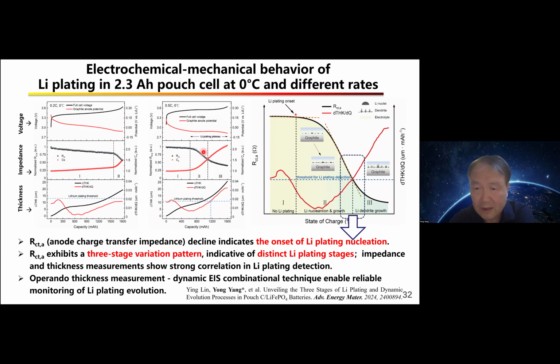We can divide lithium plating on graphite into three stages. One is without any lithium plating, starting at some stage depending on temperature and charging rate. Then there's a stage that correlates quite well with the change in EIS, changing linearly with charge transfer resistance. But at some stage, the thickness measurement can follow further the formation of lithium dendrites.